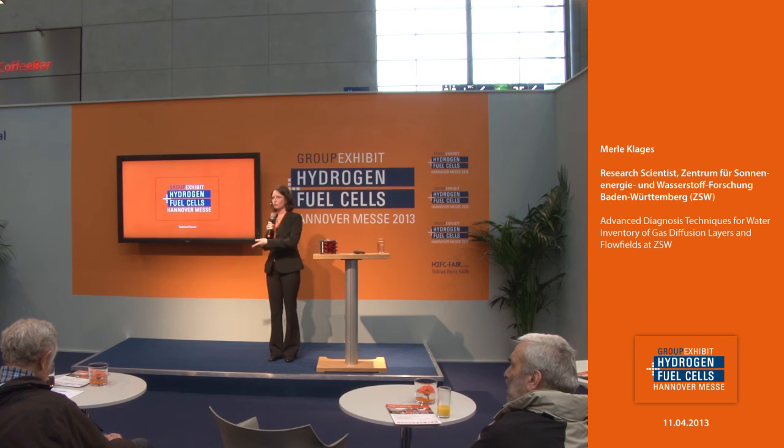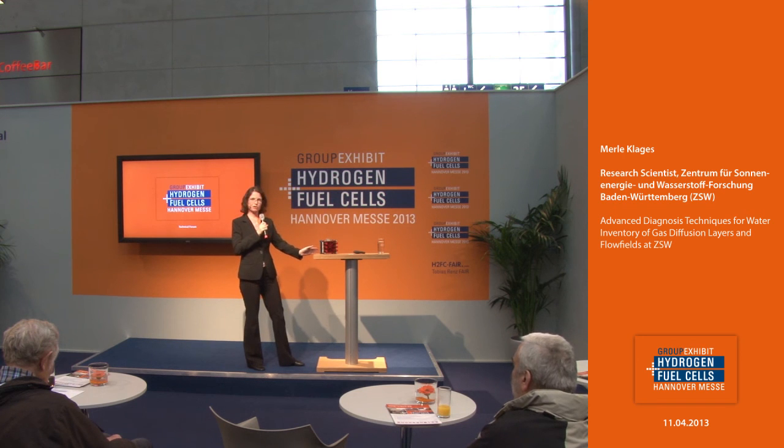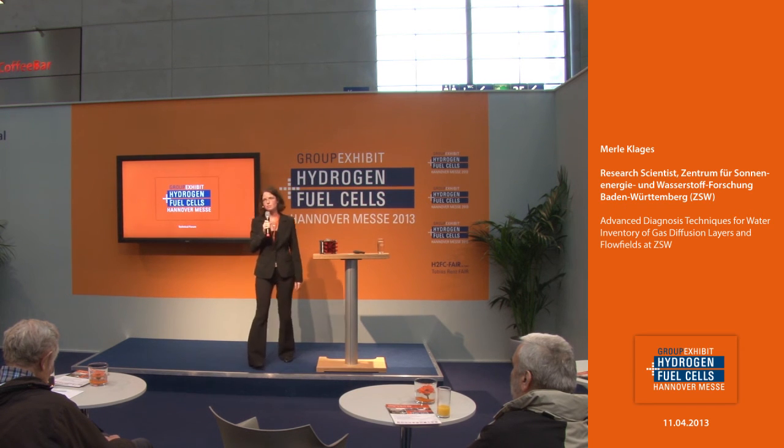What I showed here is a tomography, and tomography can only be used in stationary applications, because the fuel cell is rotated during the tomography, and that takes around 5 hours. So you cannot see the dynamics inside the fuel cell. But if you take radiography, for example, from the in-plane direction, you can see the channel and the GDL and the water coming from the GDL into the channel. So it is actually possible.